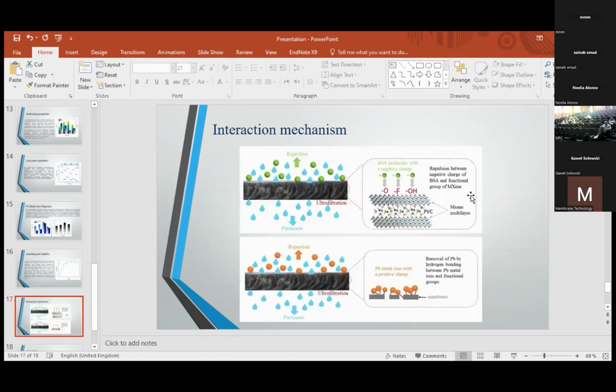The rejection mechanism in the case of BSA is determined not only by size exclusion but also by Donnan exclusion. This figure depicts how Donnan exclusion operates for a negatively charged membrane. Such a membrane rejects negatively charged contaminants such as BSA, but allows water to pass through by transporting various solutes and interrupting some ions within the membrane's channel pores. In the case of heavy metals, functional groups in MXenes such as hydroxyl, oxygen, fluorine can interact with heavy metal ions through electrostatic attraction or chemical bonding, leading to the adsorption of metal onto the MXene surface.